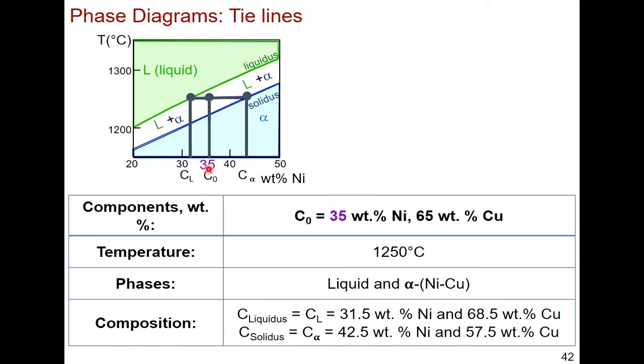Okay, so you mark where you are, but how do you know that you're here? Well, I said, for the sake of this example, we're at 1250 C. You could easily be at a little bit over 1200 C. Let's say you're right here. That will change the composition of liquid, so Cl and C alpha will be different, but C naught is not different, right? So if I'm just going up and down in temperature right here, I haven't changed C naught. I haven't changed the amount of nickel that's in my system. I've just changed the temperature. And when I change the temperature, I change where I am in terms of the tie line. I change the isotherm. Right?